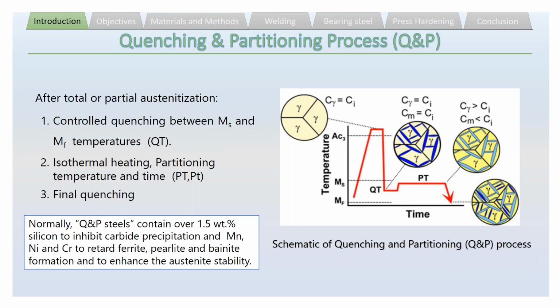Depending on the chemical composition and the time and temperature of partitioning, it's possible that we get other phases like bainite or other ferritic structures. But normally QP steels contain over 1.5 weight% silicon to inhibit carbide precipitation, because carbides consume this carbon and then there is a lower chance to stabilize austenite. In addition, most of the QP steels are designed to contain manganese, nickel, and chromium to retard ferritic and bainitic transformation and to increase the austenite stability.